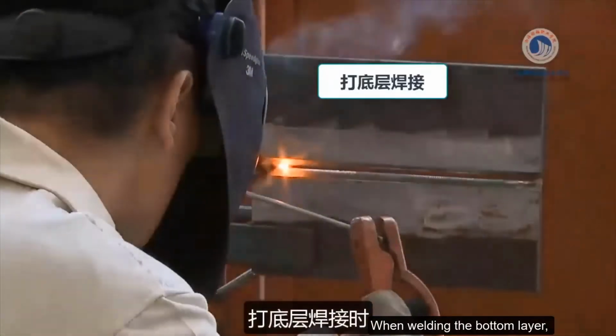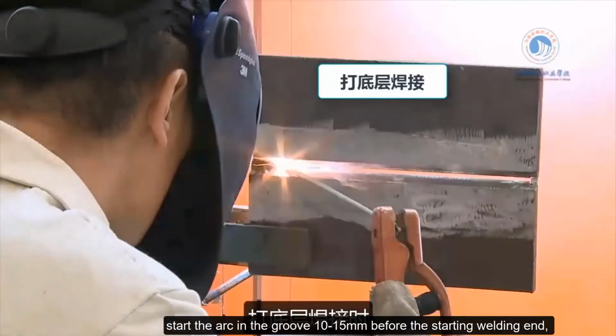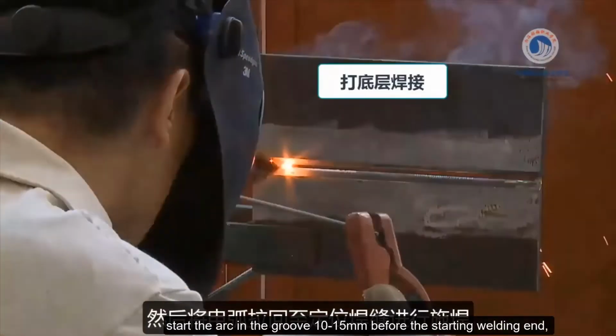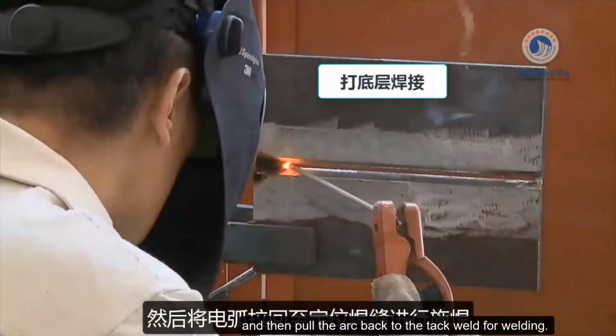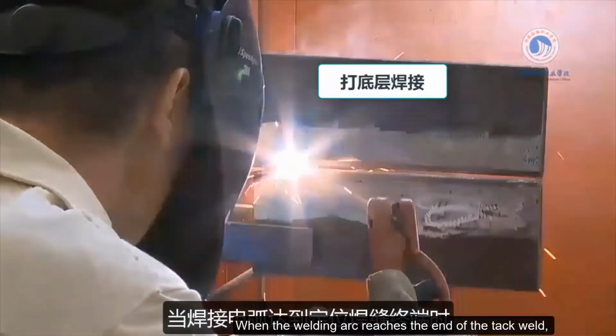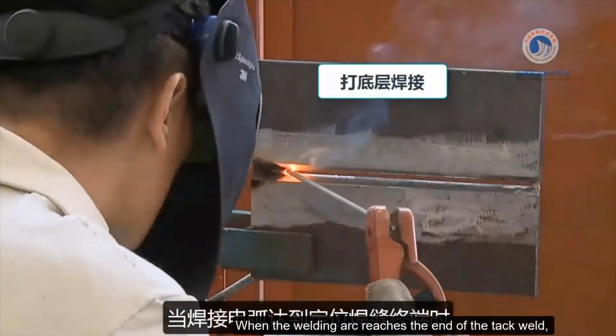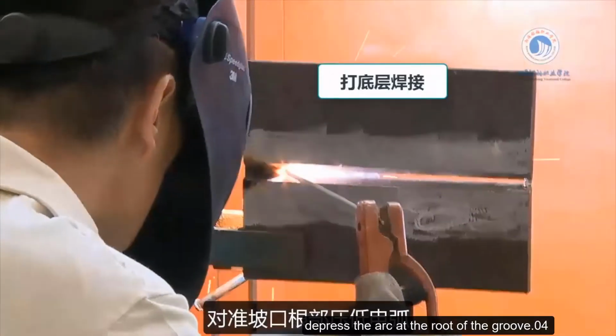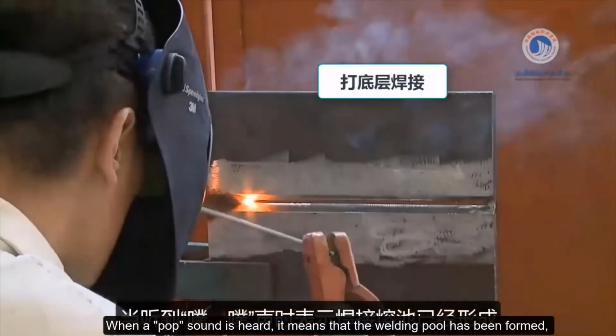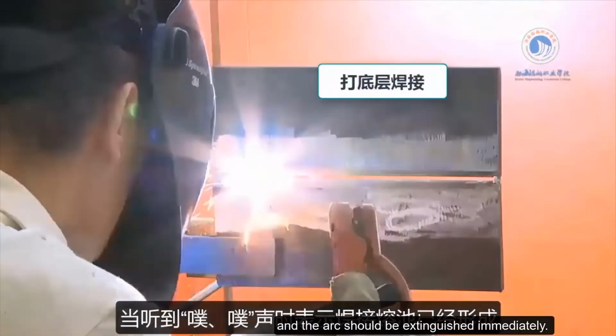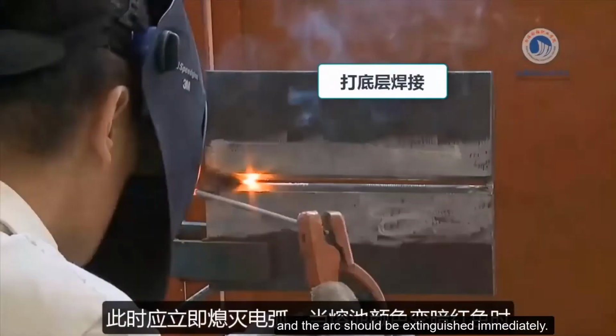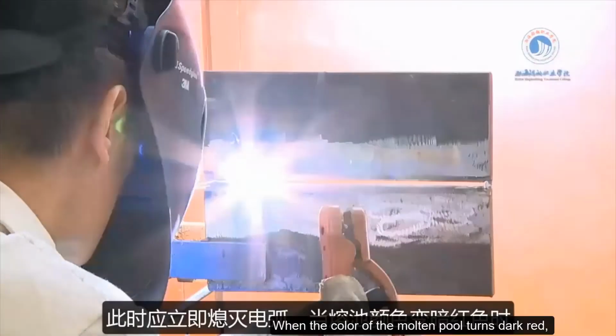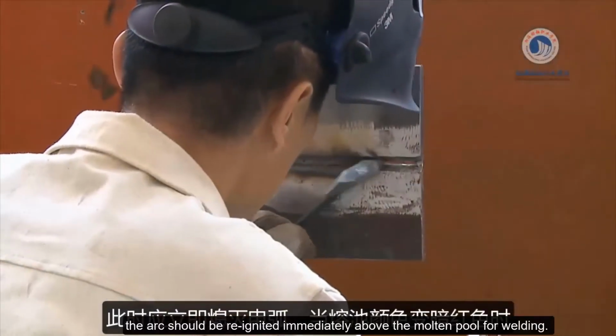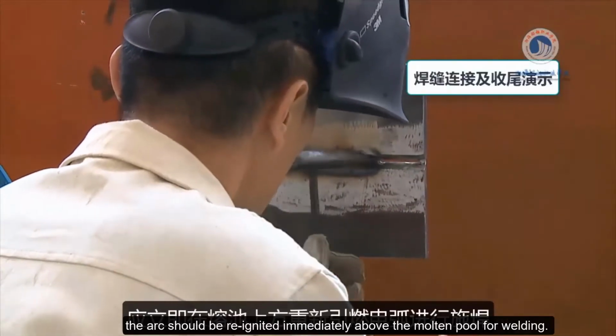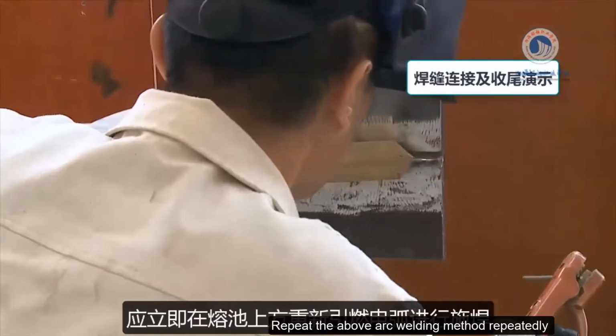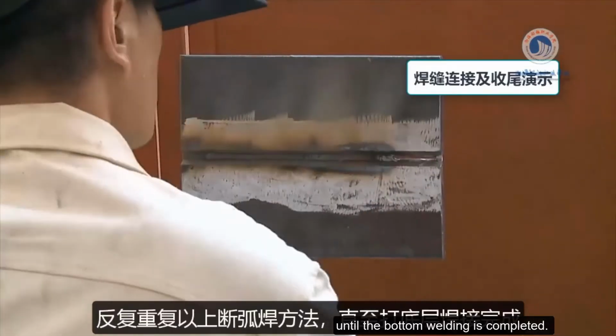When welding the bottom layer, start the arc in the groove 10 to 15 mm before the starting welding end, and then pull the arc back to the tack weld for welding. When the welding arc reaches the end of the tack weld, depress the arc at the root of the groove. When a pop sound is heard, it means that the welding pool has been formed, and the arc should be extinguished immediately. When the color of the molten pool turns dark red, the arc should be reignited immediately above the molten pool for welding. Repeat the above arc welding method repeatedly until the bottom welding is completed.